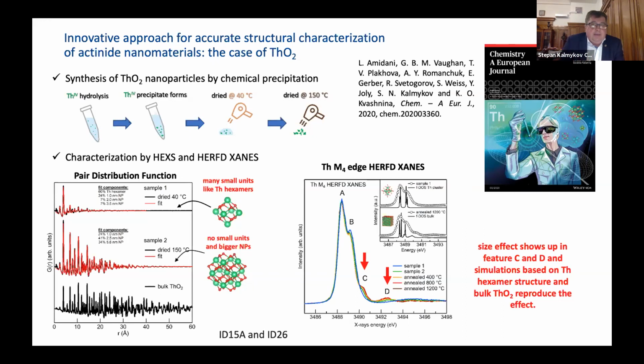When we increase the temperature, the particles start to grow, and we don't have any more hexamers. We don't have any more polynuclear species. We have only nanoparticles. So there's 24% of 1 nanometer particles, 2.5 nanometers is about half of the particles, and about 30% are 5.6 nanometer particles. This is a very important demonstration of the ability of PDF to characterize a complicated mixture of different nanoparticles and polynuclear species present in the solution.